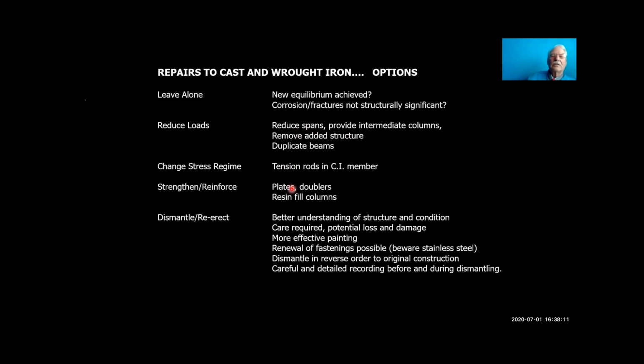Can you add plates or doublers? You can actually glue now with epoxy materials. You can glue on glass or carbon fiber, which can increase the strength hugely. And it's more or less reversible with difficulty, but it can be very effective. You could perhaps put resin inside columns to give them additional strength, although that's not reversible.